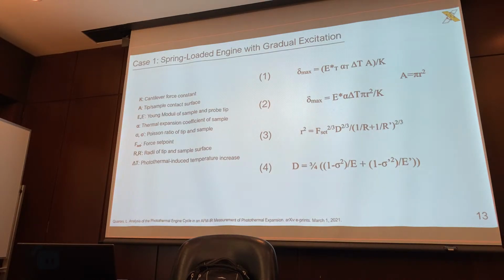So we can plug in a value for area, pi r squared, in equation 2. And in terms of equation 3, we can break down r into a combination of the radii of the tip and sample surface, and we can make it a function of this force set point that we automatically set in the instrument. So this will correspond later with a higher deflection limit. And we can break down D. D is a function of Poisson's ratio as well as the Young's moduli of the sample and tip. I don't have a term for D, but this is a factor that they inserted into equation 3. So we'll break all this down into a chart later to make it much more digestible.